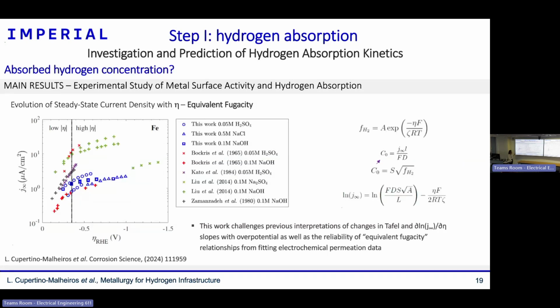And when it comes to hydrogen absorption, the first thing I did was take the permeation data. With the permeation data, we can get, using the equations on that side, a relationship between the pressure of hydrogen and the electrochemical charging, the equivalence between the two charging methods. The pressure of hydrogen is illustrated here by fugacity, and the electrochemical charging by a potential. This was an approach using permeation measurements to get two constants to be able to do this equivalence between those two mediums.